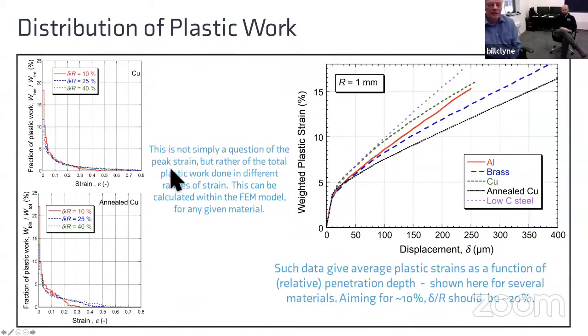If you want to go deeper into this, you could do something like this. You could say, during the FE simulation, I can note what fraction of the total plastic work is done in different ranges of plastic strain. Obviously, the deeper you go, the more you're going to get work done at slightly higher strains. But you can convert this kind of modeling to this. You can find out the average, the weighted average plastic strain that's been generated as a function of how deep you go. So this again is for 1 millimeter indenter radius.